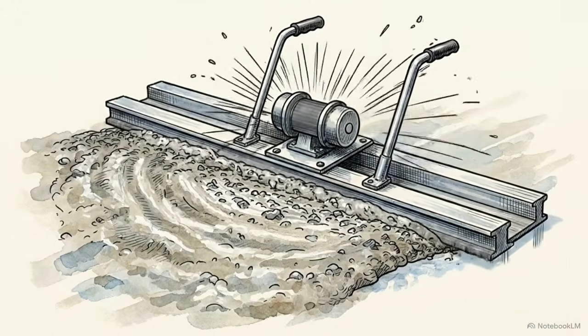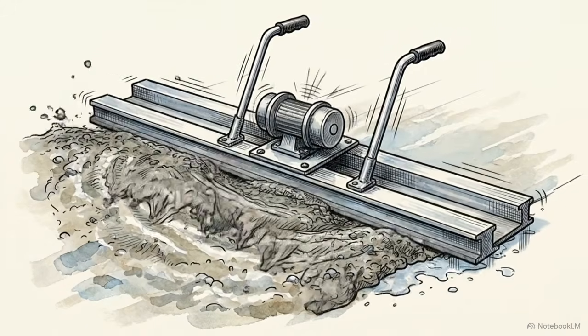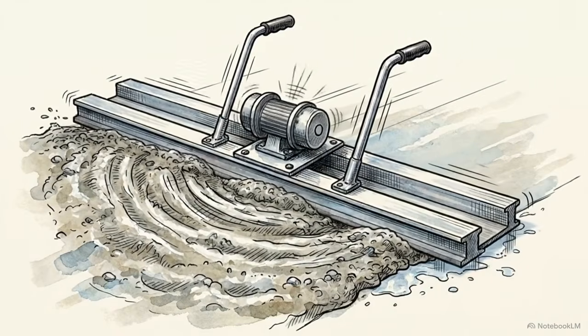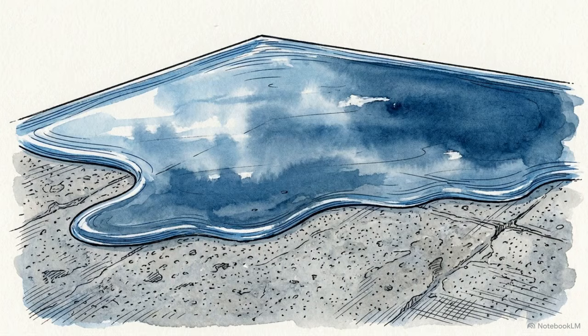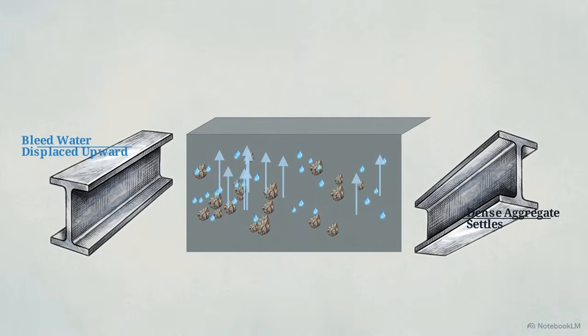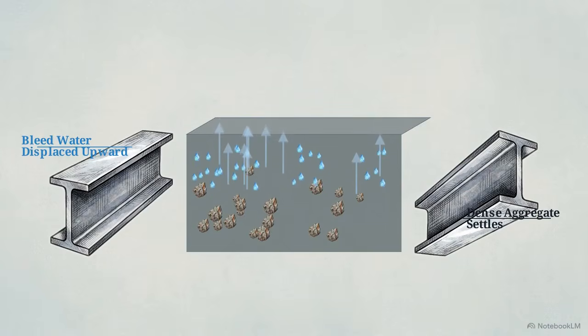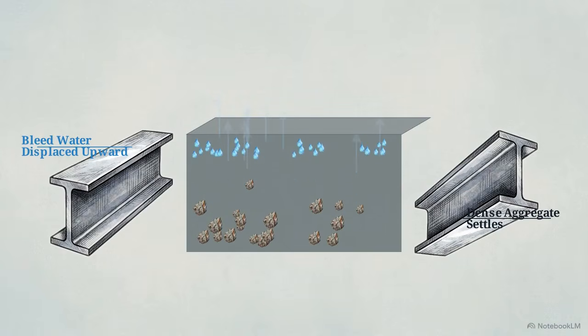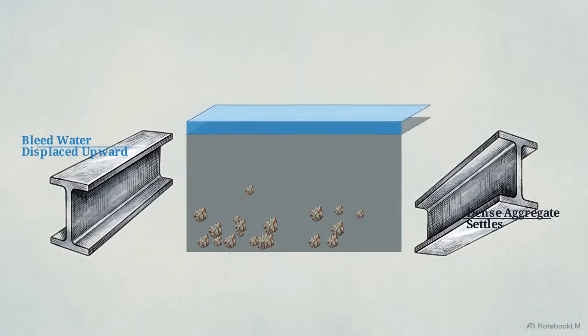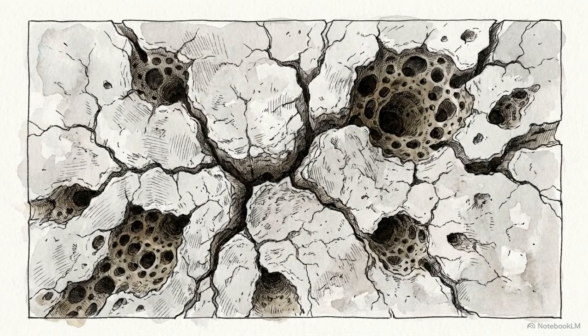As the screed passes over the mix, its aggressive downward vibration forces the heaviest stone aggregates to settle deep into the formwork. This downward settling triggers a physical displacement. Excess fluid, known as bleed water, is pushed upward toward the surface of the slab. This 3D cross-section maps the internal migration. While the dense aggregate particles sink to the bottom, the displaced bleed water is forced upward to pool across the entire upper surface layer. Without immediate mechanical intervention, this pooled water will eventually evaporate, leaving behind structural voids and a surface layer prone to failure.